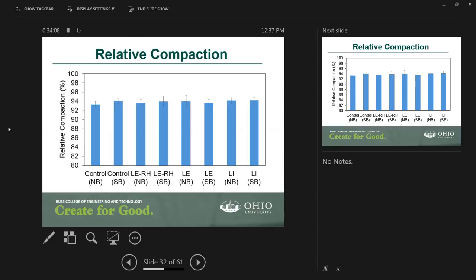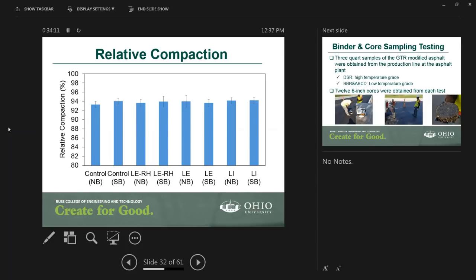And this is showing the relative density. So there was no problem in achieving the target relative density. One thing I would like to note here is that in general, the relative compaction or relative density for the GTR was slightly higher than the polymer. One of the reasons is that the GTR mixes were produced at a higher temperature. The contractor wanted to make sure that the target density is achieved, so he increased the temperature of the GTR mixes. But again, there was no need for that actually.